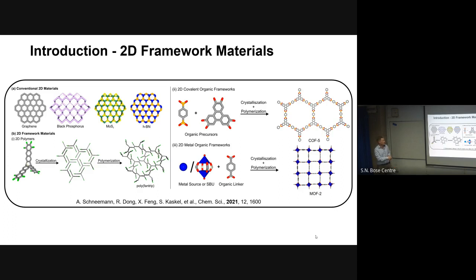With the COFs, it's a bit different. The crystallization and the polymerization are happening at the same time, which means that the materials are not so crystalline. And the metal organic frameworks, for them it's in a similar fashion. So you have your metal SBU and your organic linker. They are arranging while they are crystallizing, while they are polymerizing the building blocks.